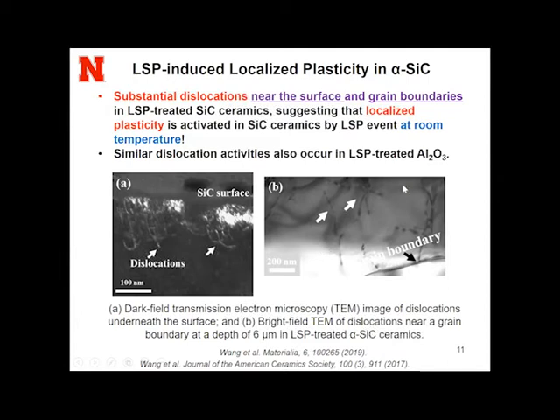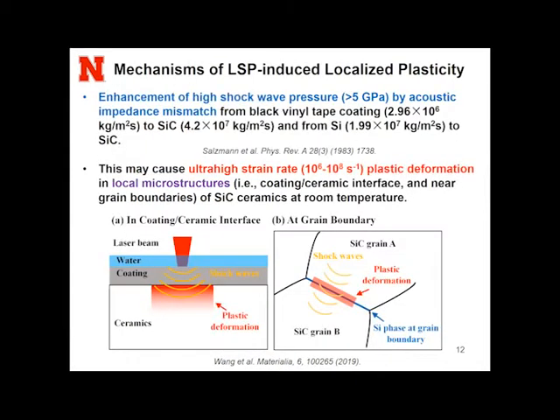And this is not only in silicon carbide, this also occurs in alumina. We published 2 different papers on this. So this seems to be a common feature. And to explain this unusual phenomenon from LaserShock peening, we went back to check some literature from a very long time ago. And what we found is